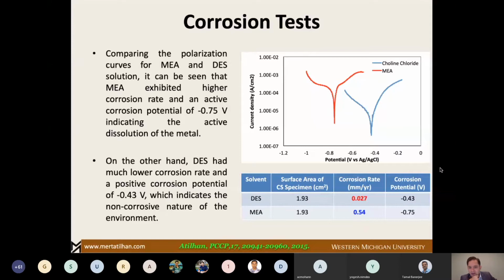I said, hey, let's give it a try. So we followed ASTM standards to do the corrosion test. At the end of the corrosion test, we repeated this 3 times, the choline chloride levulinic acid was giving us 0.027 millimeter corrosion per year, whereas MEA is almost half a millimeter per year. So this was fantastic. We were expecting to see that, but 20 times less corrosion is really phenomenal. This was one of the selling points of this work. We consider this system as having decent absorbent performance and also a phenomenal corrosion rate.